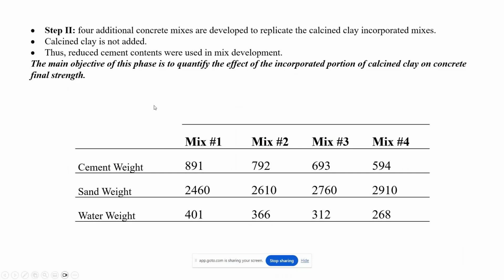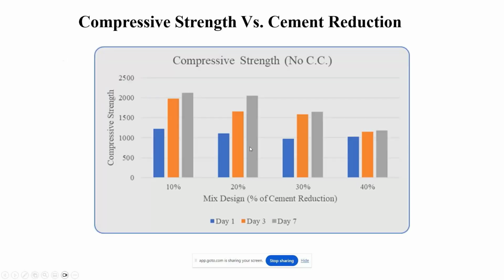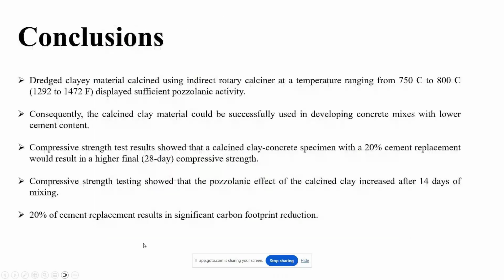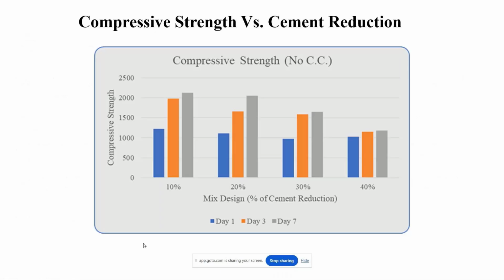Just to ensure how effective the calcined clay is, we tried the mixes, again, the control mix and other mixes, using no calcined clay. So basically just reduced cement weight and no calcined clay. We wanted to make sure that the calcined clay is having a really good effect. And we can see here at days 1 through 7 that we're having a dramatic decrease in the strength. So if you compare this 40% or this 30 or 20% even without calcined clay and reduced cement versus calcined clay and reduced cement, we have seen significant impact of the calcined clay, showing a very promising contribution of this calcined clay on the strength of concrete.